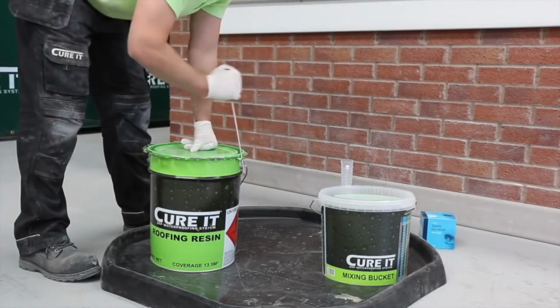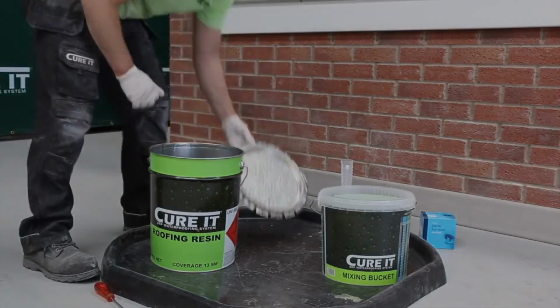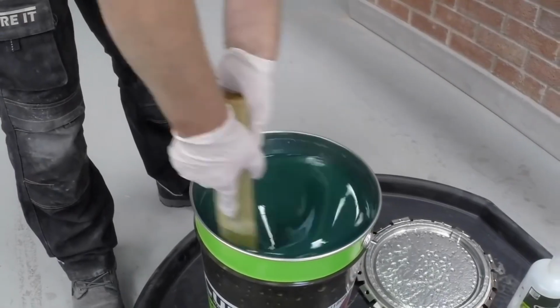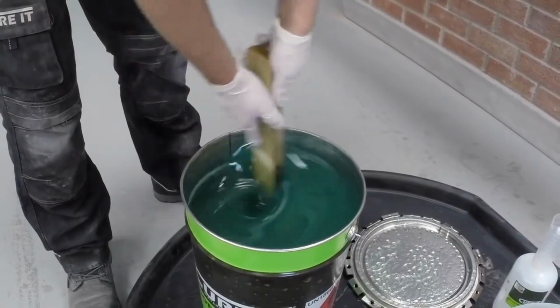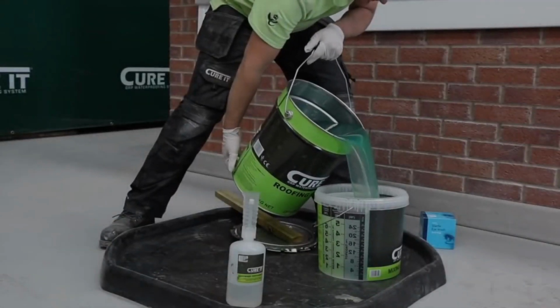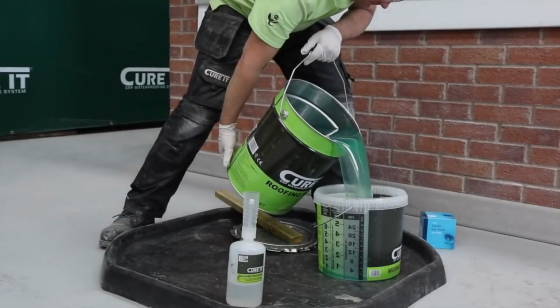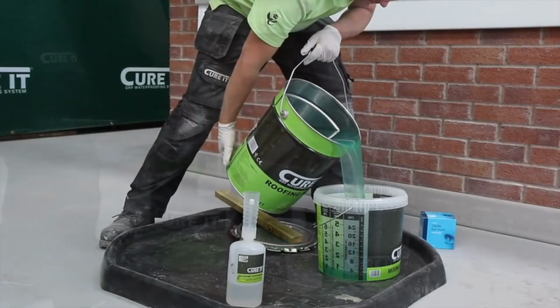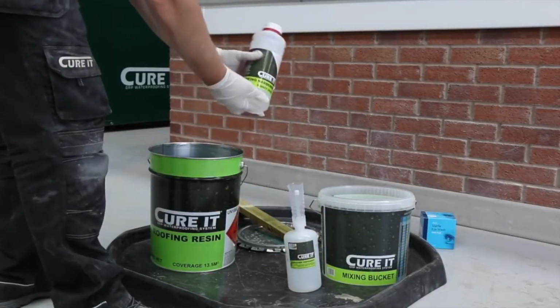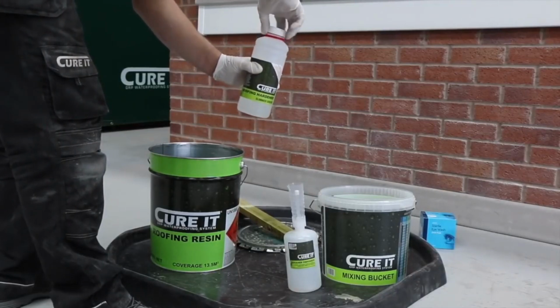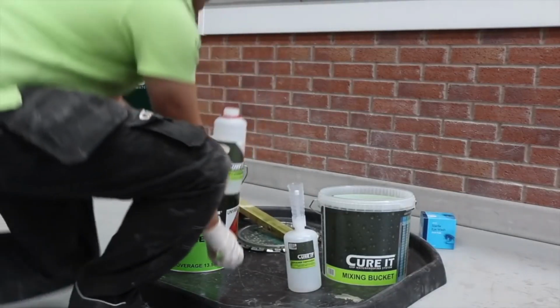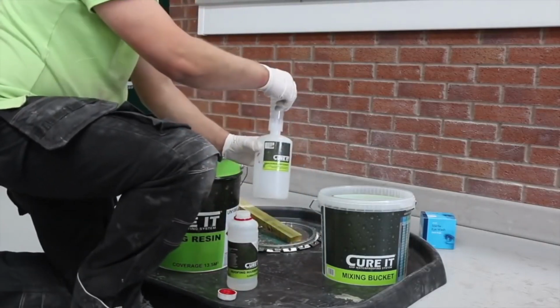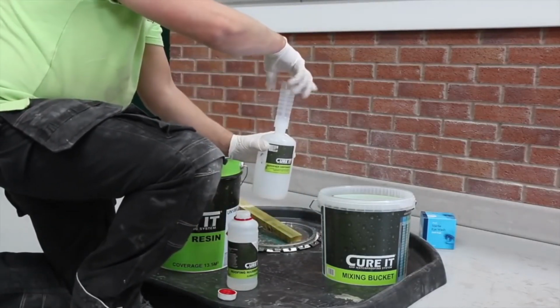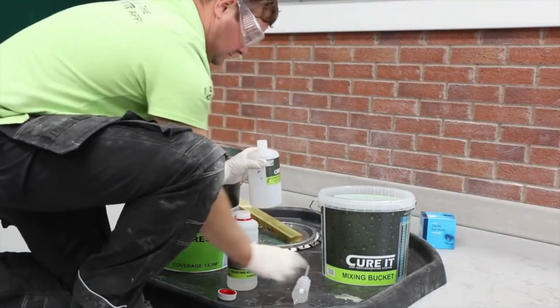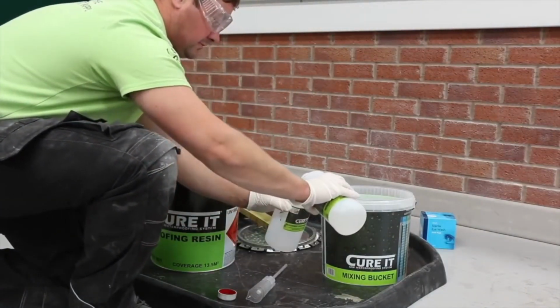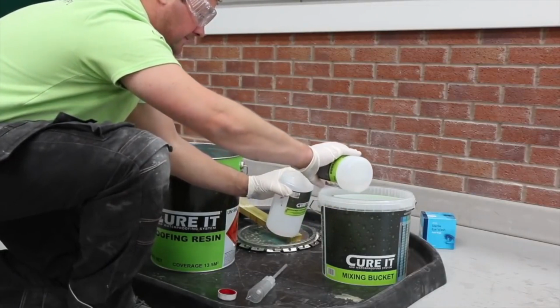Ensure that you wear latex gloves and safety goggles when using resin, and always have eye wash available as a precaution. Using the lid opener tool, open the can of resin and mix well for 30 seconds with a slate batten before pouring the resin into a Cure It mixing bucket. Start with 1 meter square for detail and tissue work. Take particular care when handling the hardener. Always read the handling and storage instructions and safety data sheet before use. Wearing safety goggles and gloves, pour the hardener into the safety dispenser. Roofing resin and top coat requires a hardener to cure.